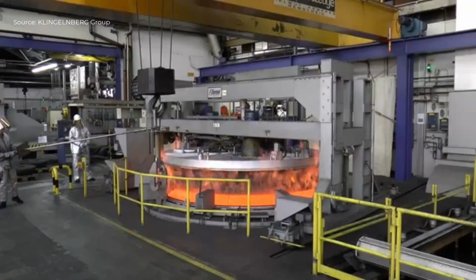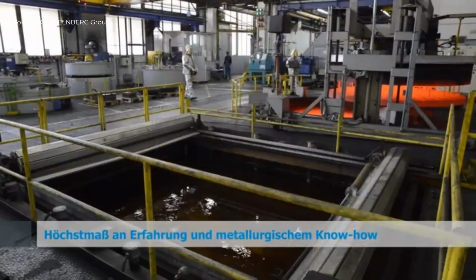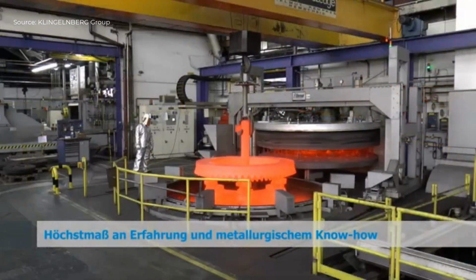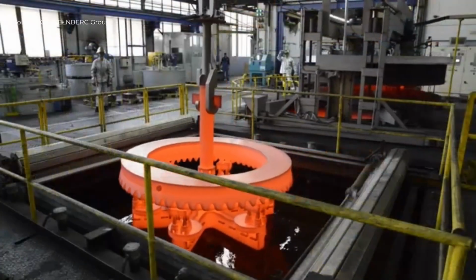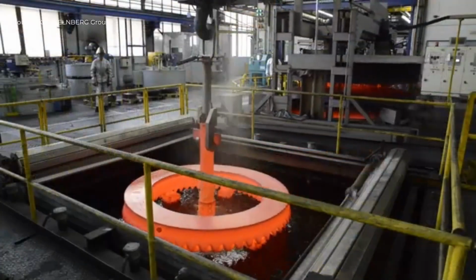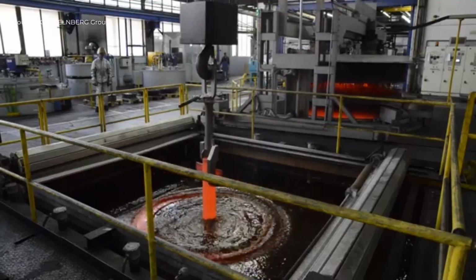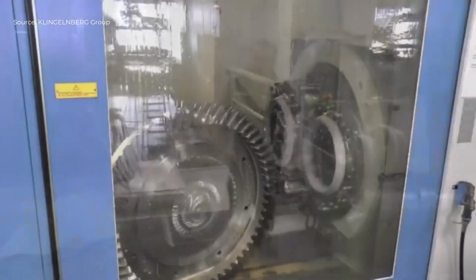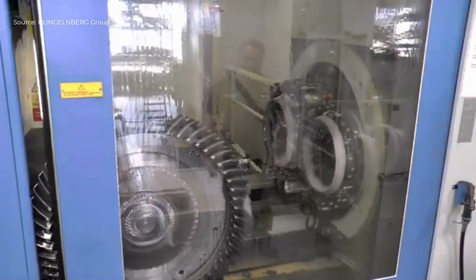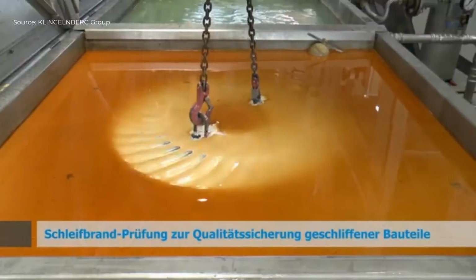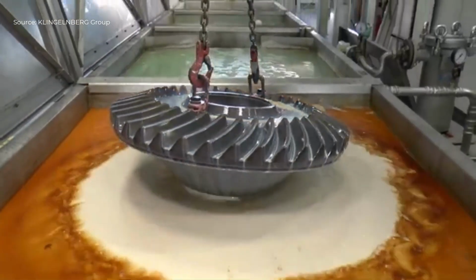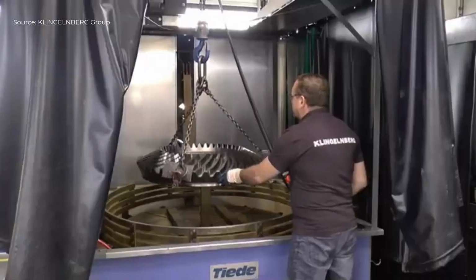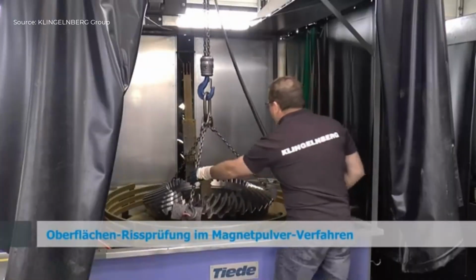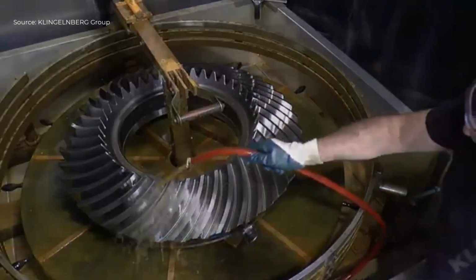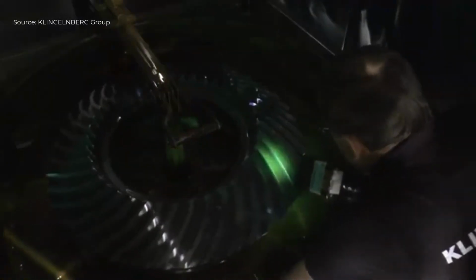After machining, parts are heat-treated in the in-house hardening shop with a monthly capacity of 140 tons. Ground bevel gears up to 1,100 millimeters are produced cost-effectively, with strict grinding burn tests to ensure quality. Surface crack inspection is performed using the magnetic particle method. Quality assurance is prioritized throughout the process, supported by contact pattern testing machines. A final inspection and customer acceptance take place directly at the facility, ensuring traceable quality. Finally, trained personnel manage optimized shipping to guarantee safe and timely delivery of the finished gears.